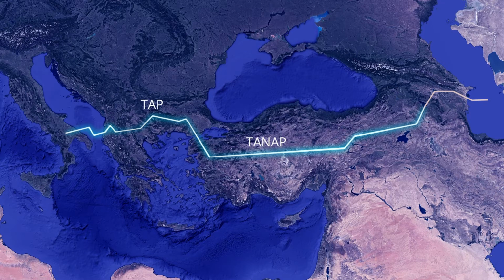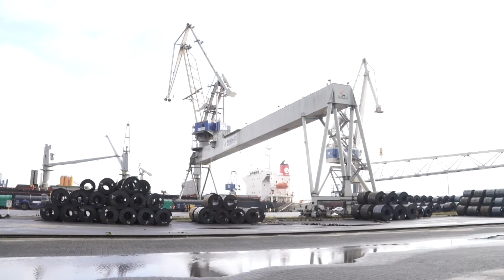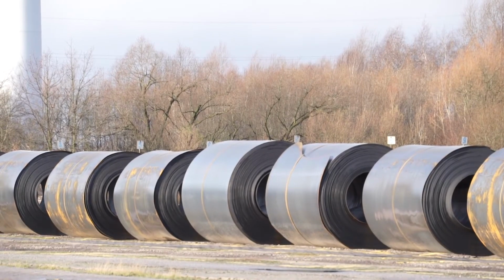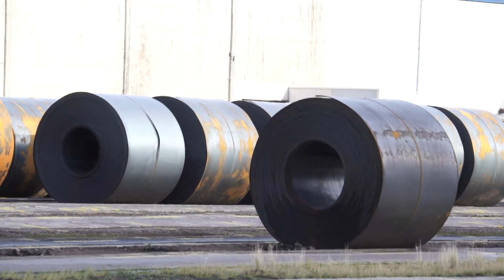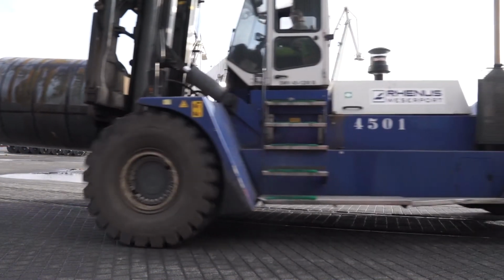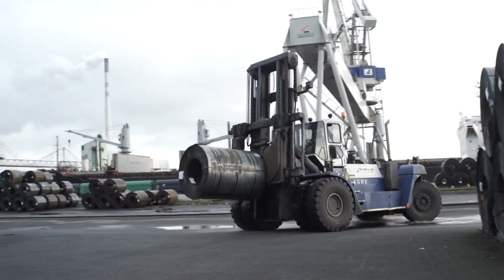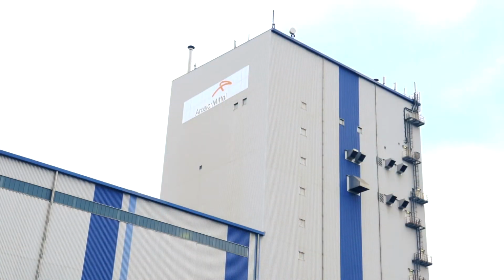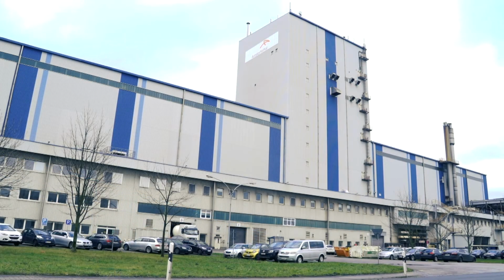Grade was X70. In high thicknesses, two main thicknesses, it was more than 16 mm and 19.63 mm. Specification was a mix between high strength, X70, high thicknesses, that I just mentioned, but also very strict and severe toughness requirement on drop weight tear tests at -10 degrees on coil. So the mix of these three main parts was really difficult to achieve. And that's why our concept of low carbon and high niobium, coupled with a specific thermomechanical rolling, was really successful and allowed us to achieve these specifications.